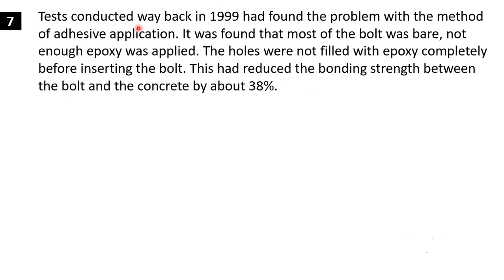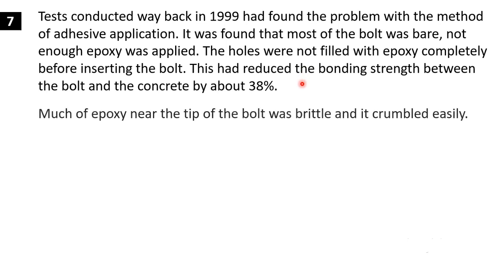A test conducted way back in 1999 had found a problem with the method of adhesive application. It was found that most of the bolt was bare; not enough epoxy was applied. So the bolt surface did not have enough epoxy. The holes were not filled with epoxy completely before inserting the bolt. This had reduced the bonding strength between the bolt and the concrete by about 38%. So it is very important that adhesive is applied properly and enough adhesive is applied so that it covers all the surfaces which are to be bonded.